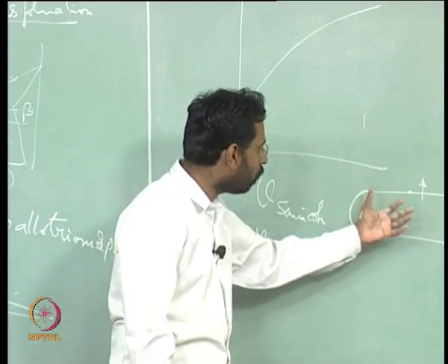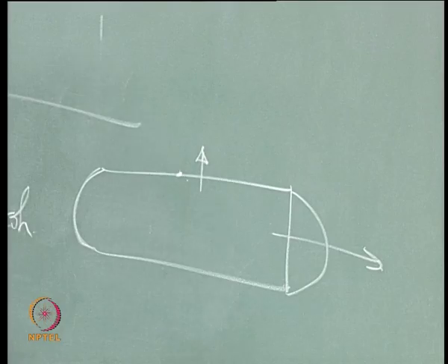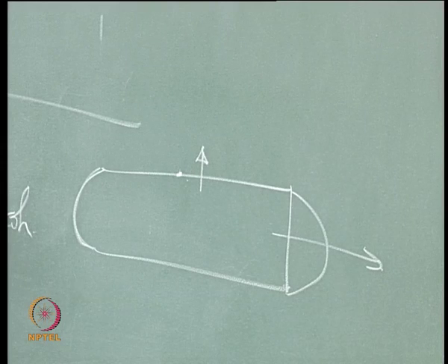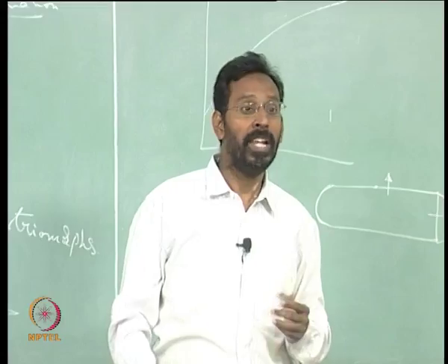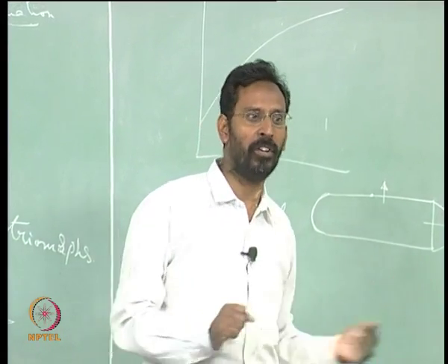Instead the system would prefer a growth in this direction. That is why in many cases you see plates coming. Even, for example, in aluminum silicon alloy, the silicon grows like needles. Even in the liquid to solid transformation you see this happening, not only solid to solid.